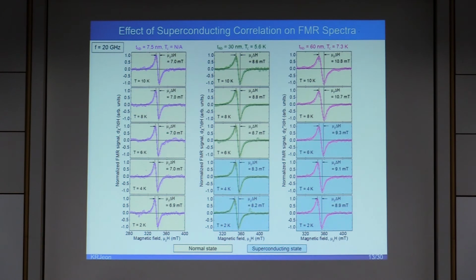Next, let me describe how the superconducting correlation influences the magnetization dynamics and spin transport by measuring temperature-dependent FMR spectra across Tc. These figures show representative data for 3 different niobium thicknesses of 7.5, 30, and 60 nanometer, obtained at a fixed microwave frequency of 20 gigahertz from 10 to 2 Kelvin.